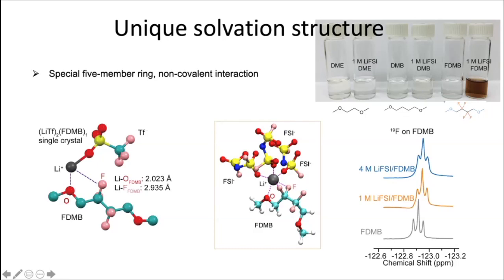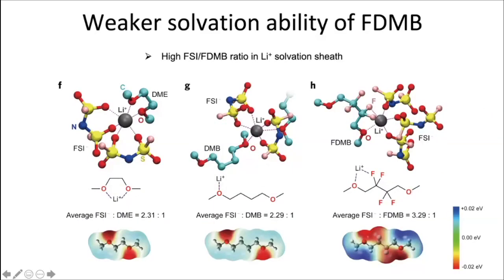And the structure for the lithium FSI is shown here. This is based on modeling. Again, the oxygen and the fluorine are participating in the solvation. In each solvated lithium ion, we see around two FSI molecules involved in the solvation. And the fluorine group's participation in the solvation can also be seen from the shift in the fluorine NMR, confirming that it is indeed participating.